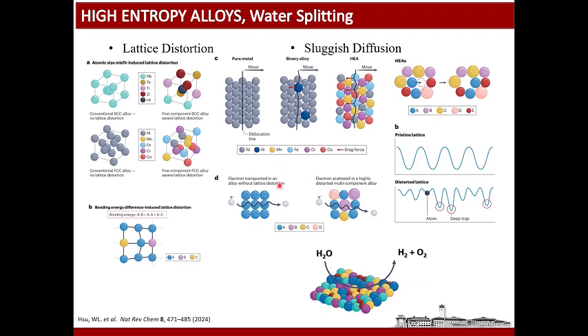And in electron transport in an alloy without any lattice distortion, since there are no scattering points, this electron transfer might be easier, but in a highly distorted multi-component alloy, that electron transfer might not be easy. So there might be localized states arising due to the interaction between these different atoms, and as a result of the distorted lattice as well. So this severe lattice distortion may increase the mobility of the charge carriers. And that will also increase the number of active sites at the surface, and the material will be able to work for this electrocatalytic application. In this case, it is water splitting reaction.